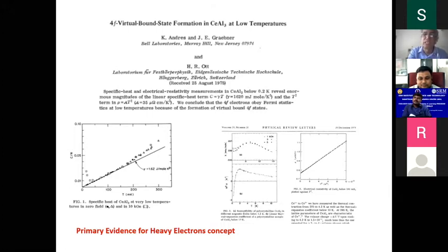So this was the T square coefficient, heat capacity, and susceptibility, as I told you here. It is very huge at low temperature. It should be somewhere very low, very small. It's very non-magnetic, but the values which you get are large. So these three terms, the T square coefficient, susceptibility, and heat capacity, are supposed to scale among themselves. Yeah, they are scaling, but the values are large.